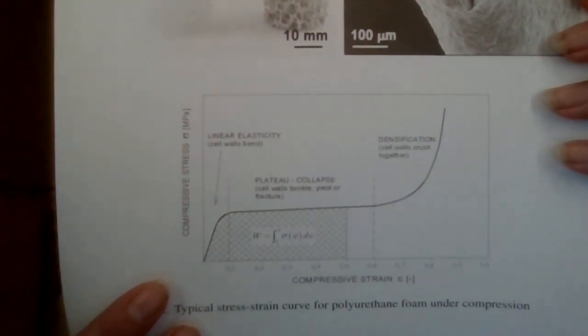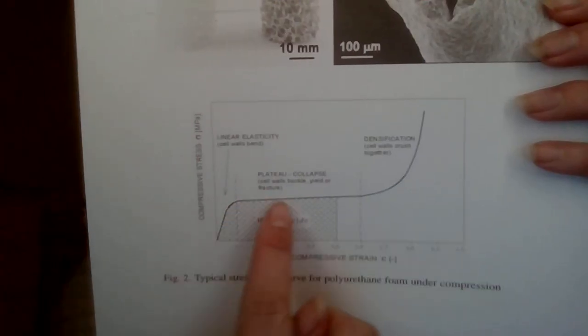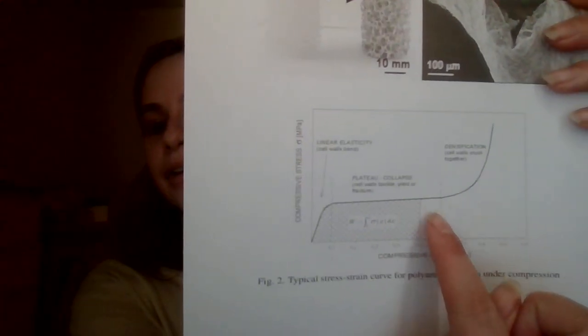But as the strain increases, we get to more of a plateau region in the stress strain curve where it starts to level out. I have a picture of that right over here. Linear region, and then this is where we get more of that partial deformation happening. During this stage, the sponge absorbs a lot of energy without requiring extra force, which is really helpful, especially if you're scrubbing really hard. But tearing can occur, and that's when you get more into the permanent deformation, much more towards the end of the stress strain curve and into the hardening region, where permanent damage really takes place. You get many more tears, like you see here and here.